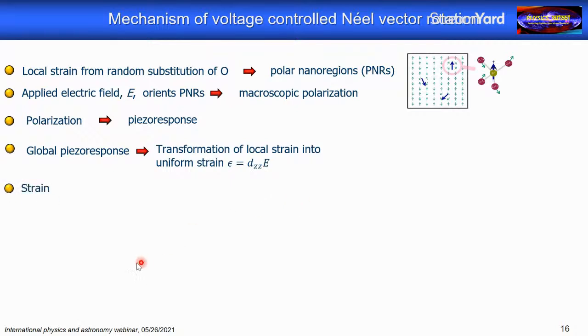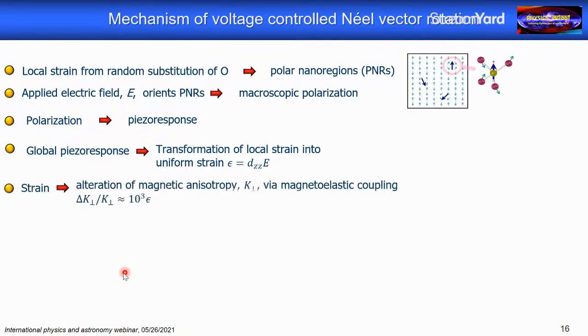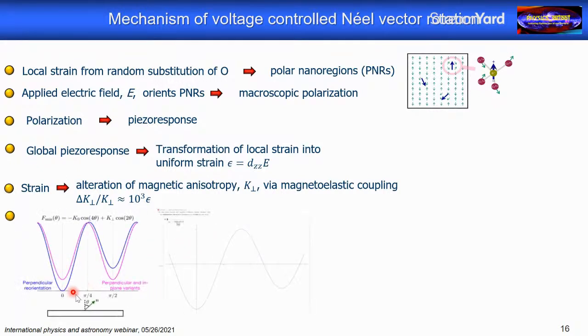So by straining, you change the anisotropy, and by changing the anisotropy, you again change the free energy landscape, making one minimum preferential over the other, so that you can switch by pure electric means between an in-plane orientation of the antiferromagnetic Néel vector, but also of the boundary magnetization, between in-plane orientation and out-of-plane orientation.